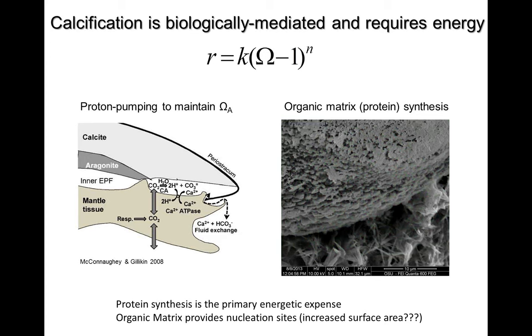And just to show you, we're kind of working on this a bit. This is an SEM image from an RU student I had in the lab, still working with us now. This is the edge of a Pacific oyster larval shell, at about 7 days, that we've decalcified. So we've removed most of the calcium carbonate that was present, left the organic material there, and then reprecipitated mineral on top of that. And what you'll notice here is that in the background you see these calcium carbonate needles, and then the precipitation that's forming on the shell without the biology present at all, this is just a dead shell, is quite different. So this is just a sneak preview of some things we're working on right now, trying to understand the role of this organic matrix and how it changes based on the physical properties, the type of mineral, and how that mineral is precipitating.